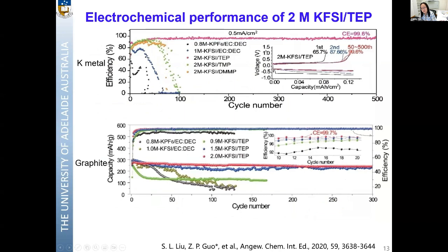We found the Coulombic efficiency quite high, average Coulombic efficiency 99.60%, suggesting the potassium plating stripping reversibility is quite good in this electrolyte. We also tested a commercial graphite anode in this electrolyte. We found it can be discharged more than 300 cycles without obvious capacity decay. And the average Coulombic efficiency, about 99.7%, is better than other carbonate-based electrolytes.